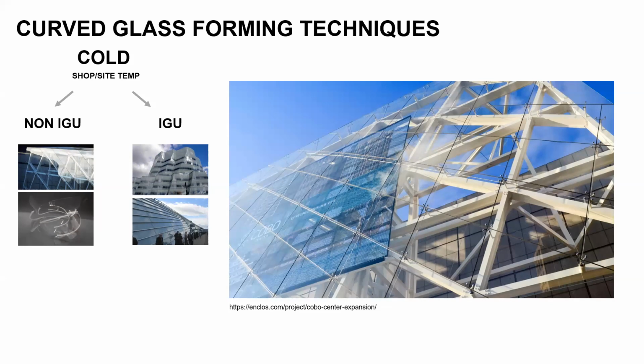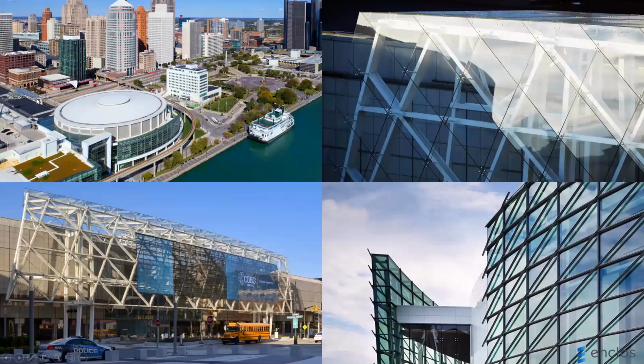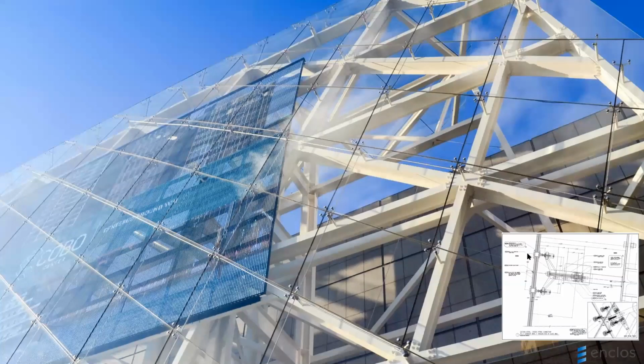One really cool application of cold bend glass laminates here, by Enclos, is the Cobo Expansion Center in Detroit, where the glass was slightly curved. The glass came planar and was deformed about 1 inch inward by means of tensioning those bolts that were at the spiders. Let me show you. That's the project, and the canopy is right there. This is the full canopy, and that's the detail I wanted to point out to you. So this is the spider here that, by going in and out, brings the glass in.